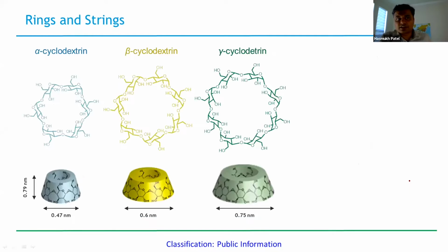We use the monomers or components. I called them rings and strings basically. So the ring components are alpha cyclodextrin, beta cyclodextrin, and gamma cyclodextrin. These are very smart molecules. We have a cavity size difference based on alpha, beta, and gamma. As we go from alpha to gamma, we have a size of 0.5 nanometer to 0.75 nanometer. The torus, that is the height of the cyclodextrin, is about 0.8 nanometers.